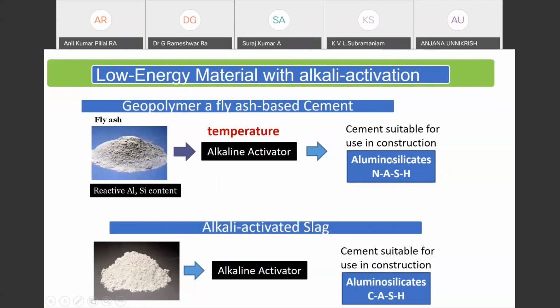able to produce a binder which goes by the name of N-A-S-H, sodium alumino-silicate hydrate, which basically is stronger than cement-based binder. And this basically does not use any energy in the processing, except of course a little bit of temperature that may be required for curing, to produce binders which are stronger than cement. And these alternate binders have been researched quite extensively in the last decade or so, and now they're slowly finding their way into mainstream use.